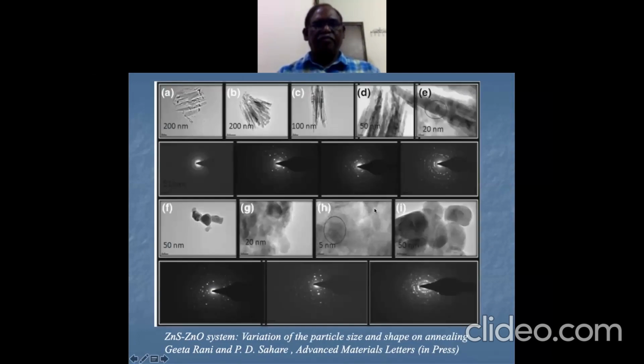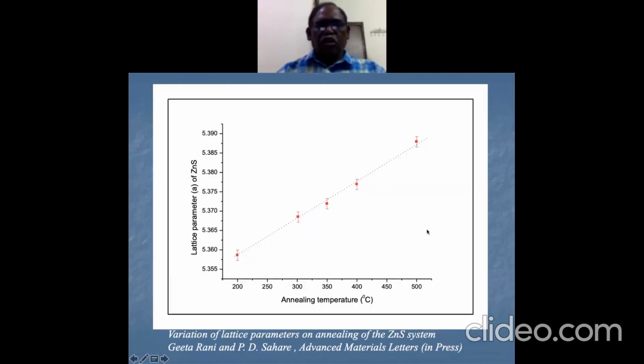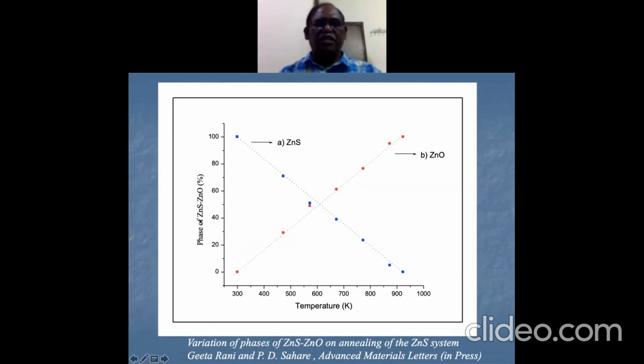But ZnS is in cubic phase, and ZnO is hexagonal, and therefore by annealing we have prepared this in rod form. So by annealing there is a stress developed, and because of that the nanorods break, and you get then particle size, and also at very high temperature they get bigger in size. So with annealing temperature, you will see that the lattice parameters also change because of the composite system, as some ZnS gets converted into ZnO. And here also you can see the percentage of phase: one phase goes on reducing, and the percentage of another phase goes on increasing.